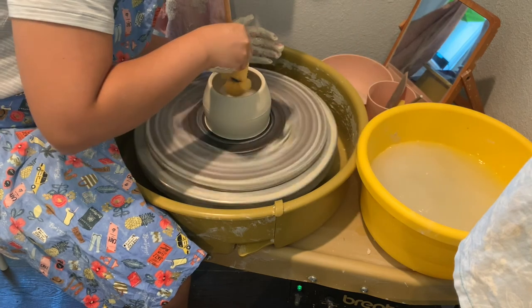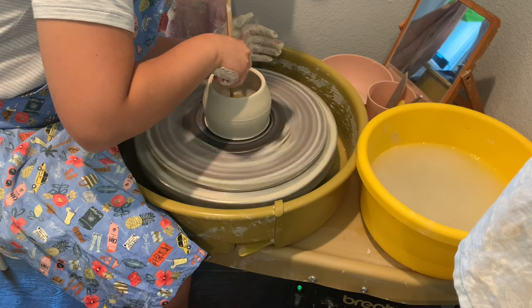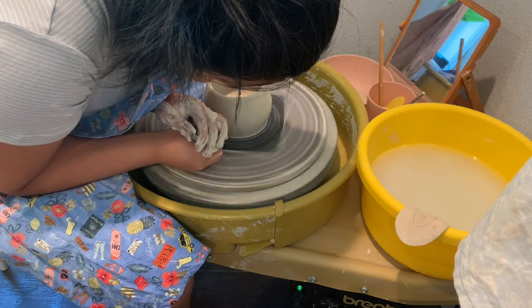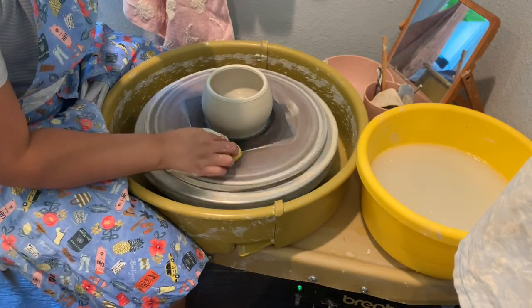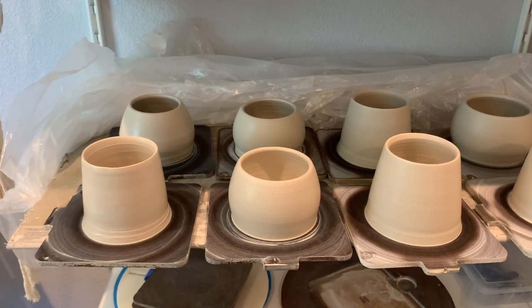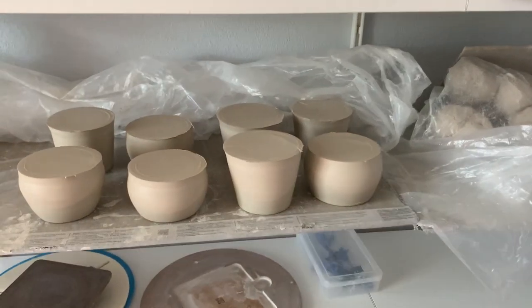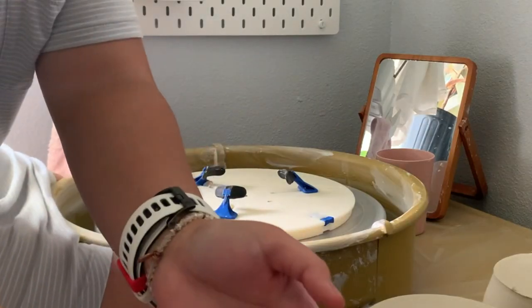So what I'm making here are about six pink boba mugs and six jackalope planters, and throwing and sculpting them in a batch made the process a lot easier than before. Summer here has been very hot — it's been 100 degrees — and my pieces would dry out way too fast, and they tend to have hairline cracks when they dry too fast. After I finish these pieces I wrap them up in plastic and let them slow dry to prevent hairline cracks.